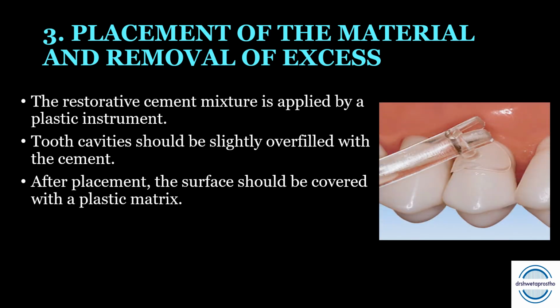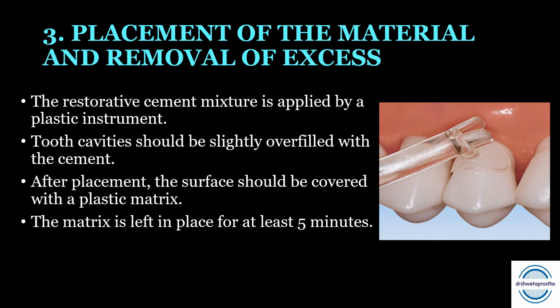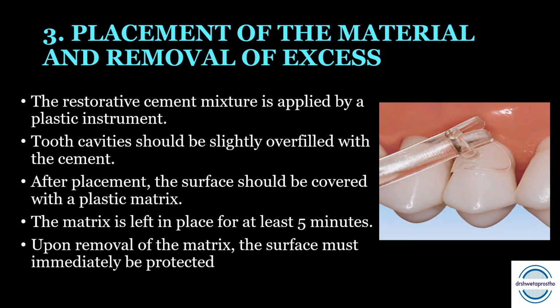This is very important because this protects the cement from the environment, from losing or gaining water during the initial set. The matrix is left in place for at least 5 minutes, and then after removal of the matrix, the excess material should be trimmed off from the margins.